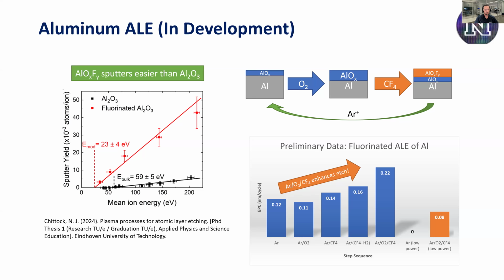Maybe there's a way that we can modify that if we can control the aluminum oxide thickness and then modify that controlled layer, not all the way into the aluminum, but a little bit, and then remove that modified bit. We'd have a 3-step process where we're oxidizing the surface, modifying it, in this case with CF4, and then removing just that modified bit and doing that cyclically. We might be in a good place.